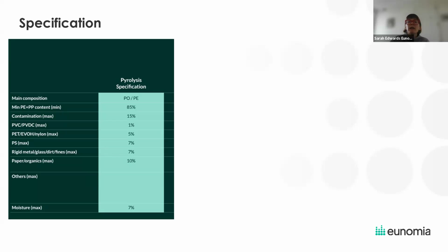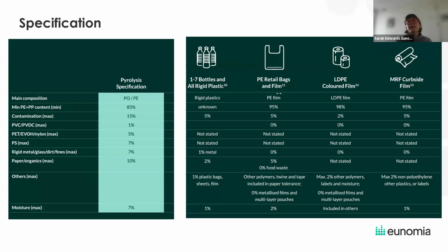So how does this compare to current specifications on the market? I've just highlighted here specifications of some other plastic grades. And as you can see, the main point here is that the pyrolysis technology can take a polyolefin mix, so a PE-PP blend, and to some extent small amounts of multi-material and metals, compared to the current specifications for PE retail films and LDPE color films. That mix of polyolefin blend is obviously something that's very beneficial to the flexible packaging stream. There is also some level of contaminants that can go into that, slightly less stringent than some of the other specifications.